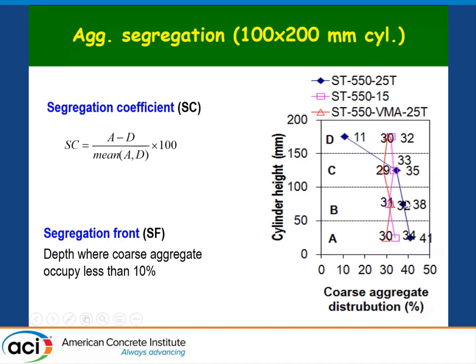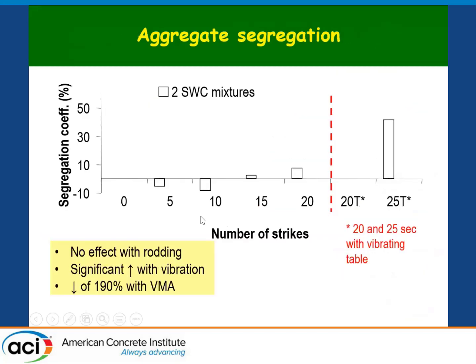So this is one concrete that segregated a lot, and the same concrete with the same slump flow. If you use 25 seconds of vibration, but using VMA, you bring it back to basically a straight line, the same as using only 15 strikes. So in terms of segregation coefficient, for super workable concrete, you can see that there's very limited effect of the striking with a small rod on segregation, and then a lot more segregation if you subject the concrete to vibration.